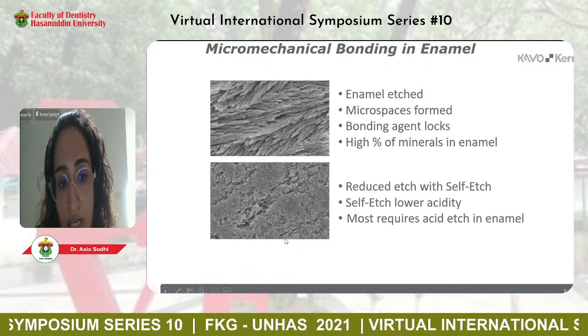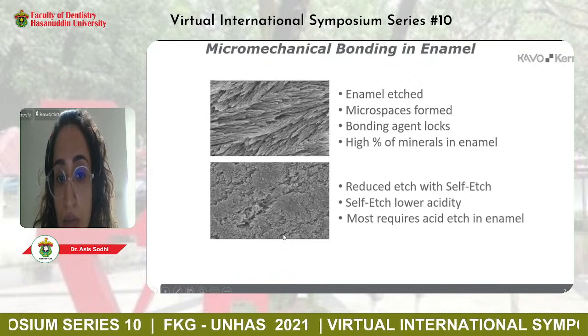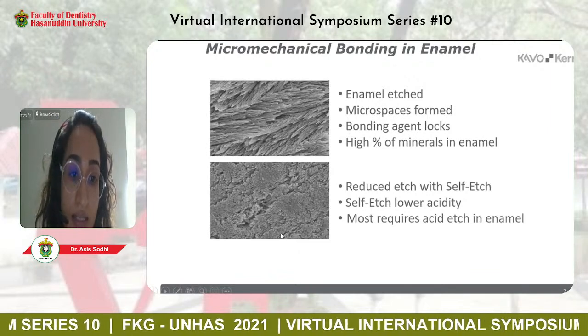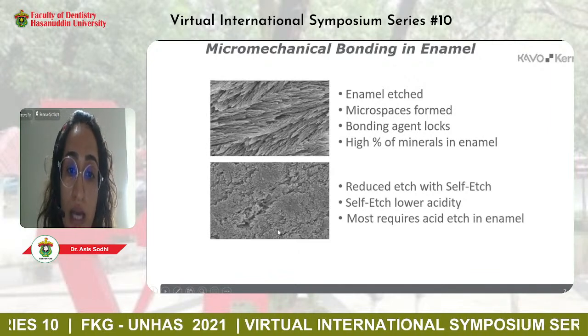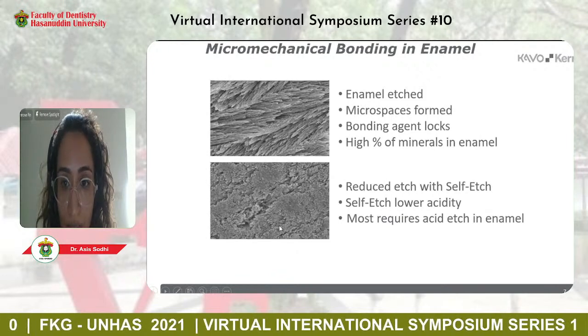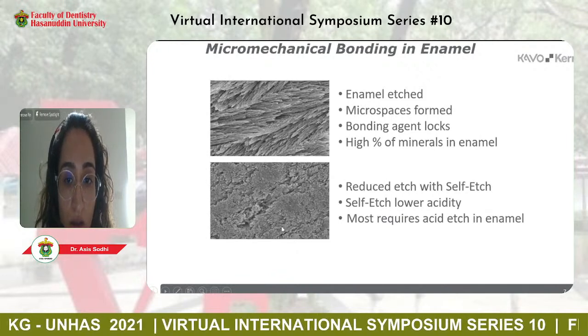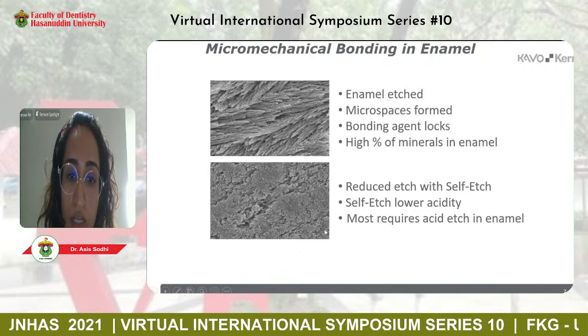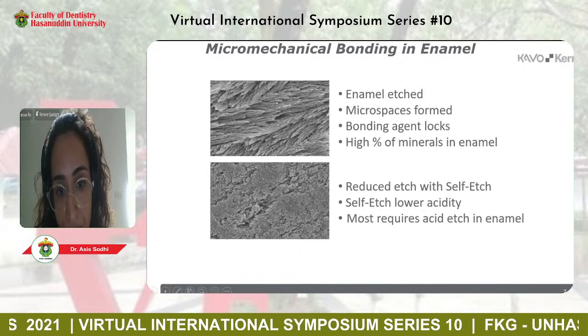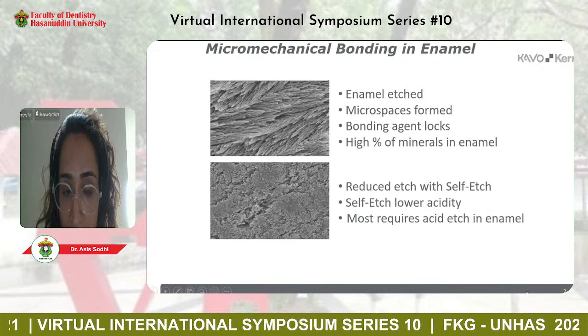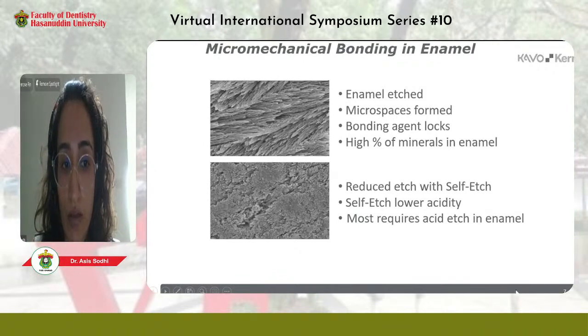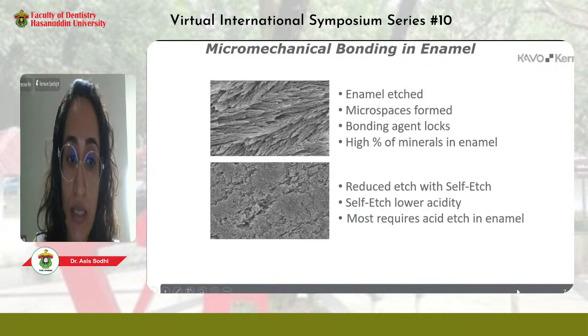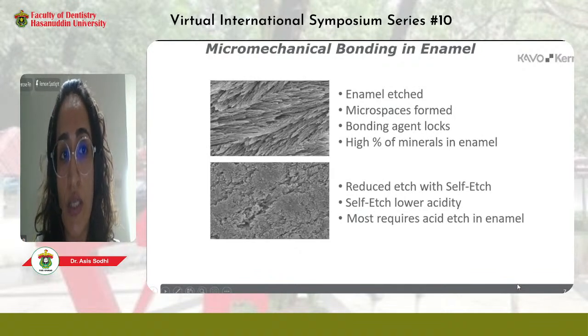Now, when you look at the second image, there is still a pattern that you see, but it isn't as aggressive. And this has been formed as a part of a self-etch process. So you've used a self-etch bonding agent. Self-etch bonding agents typically have lower acidity, and they still remove minerals from the surface, but the pattern that is formed is not as aggressive. And we will learn about the differences between self-etch and total etch in the following slides.